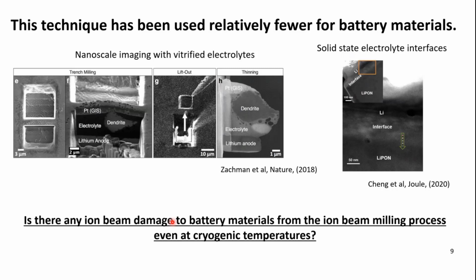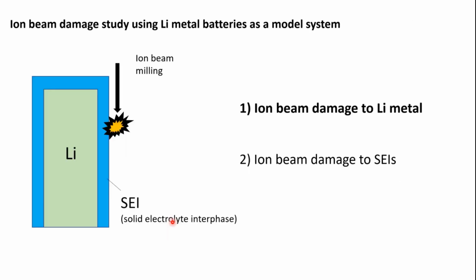And before I really started using this technique, I first investigated ion beam damage to battery materials. So I used the lithium metal battery as a model system, and I studied ion beam damage to them. As I mentioned, there are two important parts in a lithium metal battery. First is lithium, and the second part is the SEI, which surrounds the lithium metal dendrites. And I investigated ion beam damage to each part.